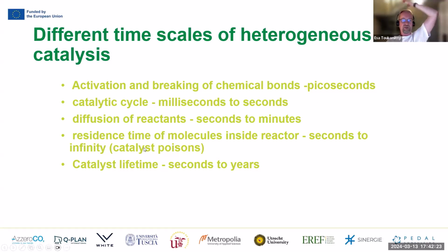And that was just the dimensions. So there are also time scales in catalysis. The active site bond breaking and chemical reactions are in the picosecond region. Then when we talk about the whole catalytic cycle, we talk about the free molecule adsorbing on the surface, migrating on the surface, dissociating, doing the chemical reaction, migrating again, adsorbing, and so on. This is a millisecond. And if you have these extrudates, this millimeter scale, the diffusion from the outer surface to the inner pores and surface can take seconds to minutes.